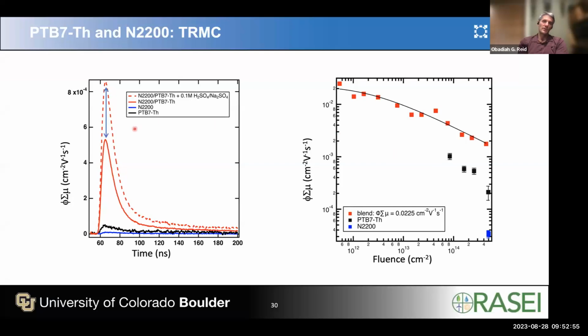And so it's my hope that if we can do these in situ measurements successfully and stably, that we can understand whether it's yield or mobility changing based on whether the curvature of this fluence-dependent plot has changed. Okay. Yeah, that will be nice. Although we've not managed to do that yet.